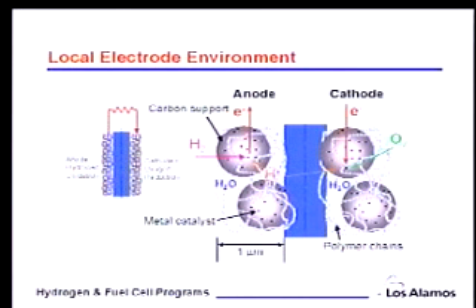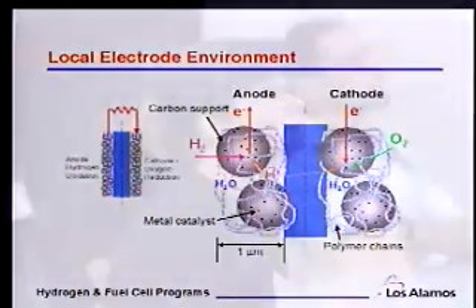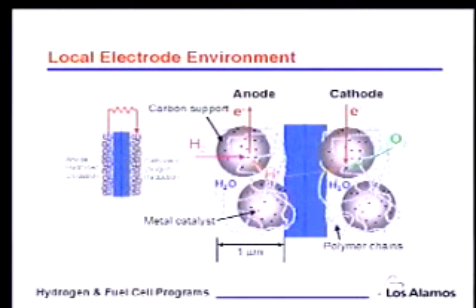If hydrogen comes in here and wants to react with that site, you get the hydrogen oxidation. What you have to have is electronic conductivity for the electrons, so that's point-to-point contact in the carbon. But you also have to have some of this ionomer close enough for that proton to migrate through the membrane over here to an oxygen catalyst site. At the same time, you also have to have enough porosity in here so that the gaseous reactants can get in. You have to humidify this because these polymers don't conduct unless they're wet. So this has to be basically hydrophilic. This has to be hydrophobic. So they're complicated structures.